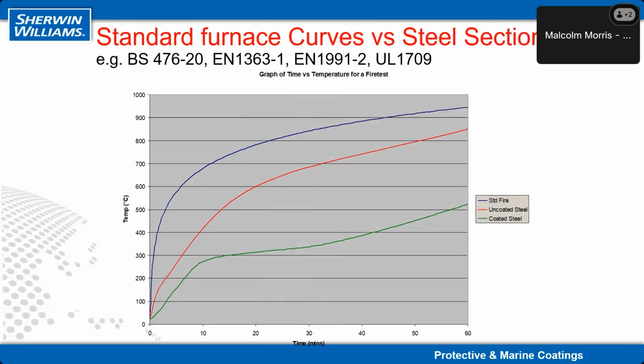So this is an example of the standard furnace curve, which is the blue line at the top, which could be defined by a British standard or European standard or American standard. And it's a similar sort of concept. The test furnace is heated up according to the blue time and temperature curve. If you put a piece of untreated, unprotected steel into that furnace, it would rise according to the red curve in the middle, which is basically following the furnace curve with a bit of a lag because of the heat sink of the steel. Then the green line at the bottom is the line which would be given by a protected piece of steel, and that will obviously stay much lower. And the aim is to keep the green line at the bottom below the critical temperature, whether it's 550 or 400 or whatever. That'll be defined by the Eurocodes.